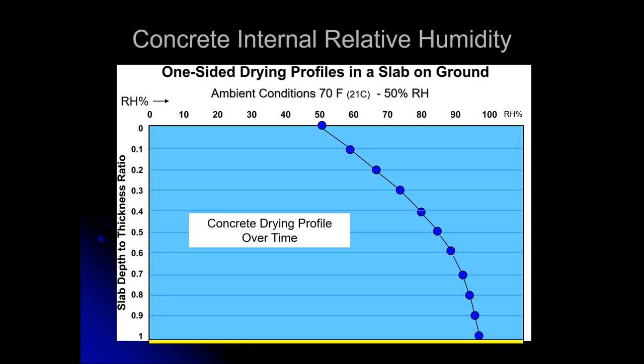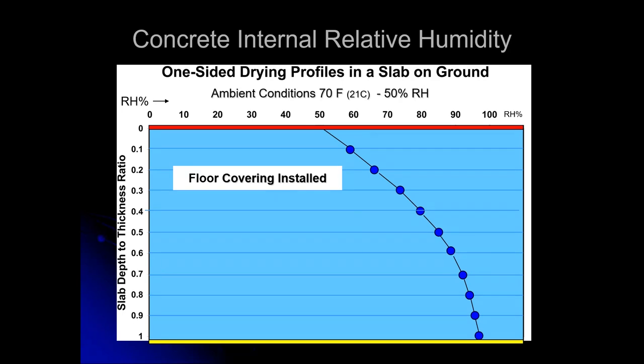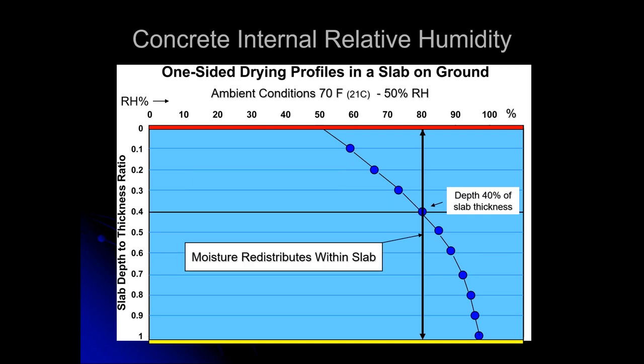But as we go deeper into the concrete, the relative humidity increases. Now, when we cover the surface of the slab with a low permeance floor covering or coating, that gradient will reestablish itself as a straight line, but because we've lost a measure of moisture, it won't be 100% anymore. It will be, in this case, 80%. And the research that was done at Lund University repeatedly showed that where the drying curve and the redistribution equilibrium state lines intersected always fell at approximately 40% of the slab thickness. So that's why a measurement in a 5-inch slab at 2 inches down is predictive of what we can expect the RH level to be top to bottom once the slab is covered.